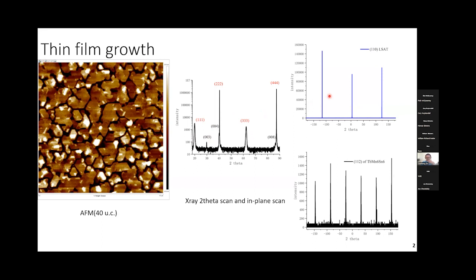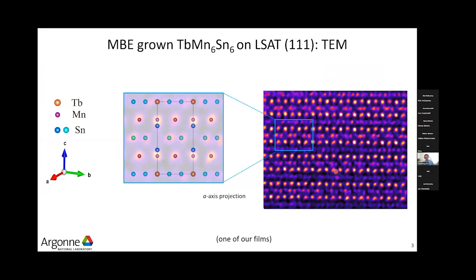And we did a phi scan to study the symmetry of the film. First we use the LSAT 110 peaks as a reference. We can see the 110 peak of the LSAT, and then we use the 112 peaks of the film to study the symmetry. We can see a good 6-fold symmetry of the thin film. And also our high resolution TEM data shows our film is in the correct phase of the terbium manganese tin structure.